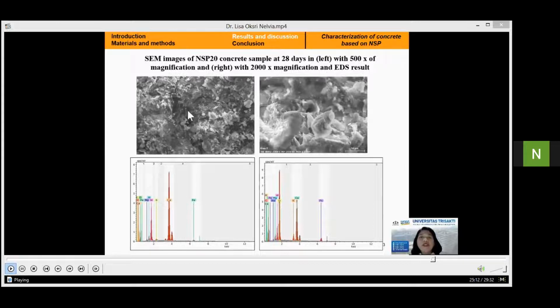In the figure top left, the SEM image was magnified 500 times. According to the result, the image formed a particle that contained mineral elements such as iron, calcium, silica, alumina, and magnesia, which is explained in the EDS result in the figure below left. In addition, the figure on the right shows the same SEM image magnified 2,000 times. This figure shows silica, calcium, and magnesia in the EDS result; the dark color indicates the presence of silica, and when it's lighter, it contains iron.